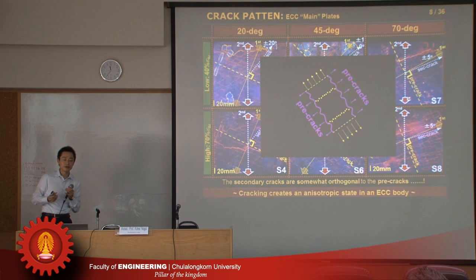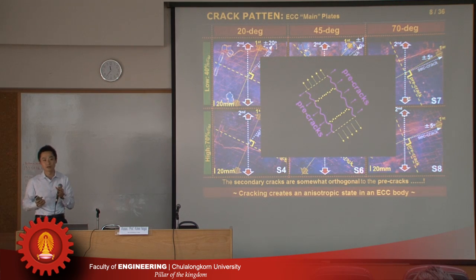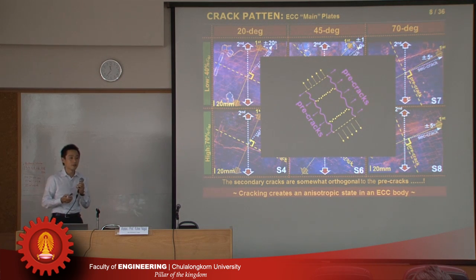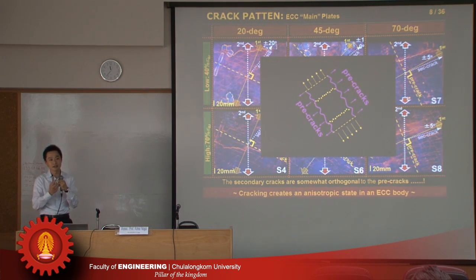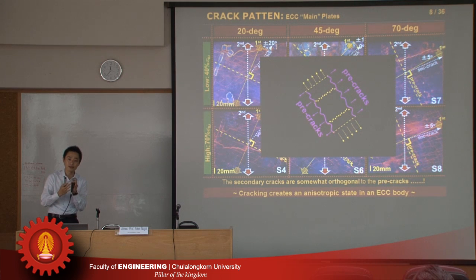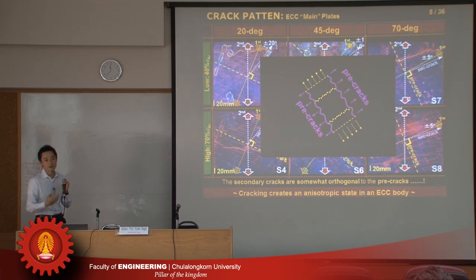So by the way, when we use normal concrete with aggregate, we don't have this kind of problem. Actually, we haven't seen this kind of phenomenon in normal concrete because we have aggregate in the concrete. When we have aggregate, even if we have an initial crack, because of the good shear resistance, the secondary crack occurs following the secondary principal direction. But when we have very weak shear performance, the sliding becomes very easy. So then, yes, an unexpected secondary crack is generated. This is what we found in this research.